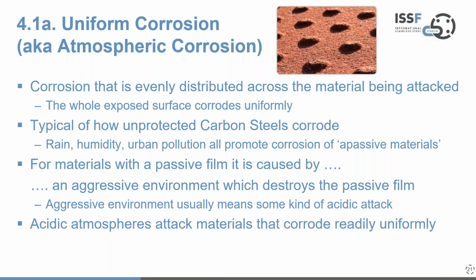But for materials with a passive film, you can also get uniform corrosion in aggressive environments, which effectively destroy that passive film. So aggressive environments usually mean some kind of acidic type attack in the case of stainless steels. And these will attack materials in a very uniform way once you've destroyed the passive film. That's not to say, though, that the passive film can't resist these forms of attack, but we have to recognize what is likely to occur to be able to resist it.